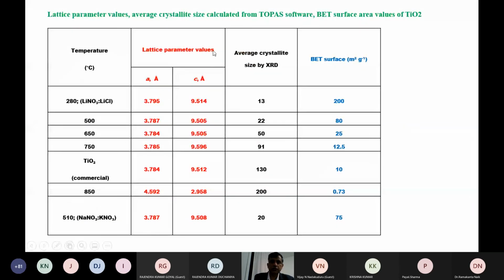Here, we try to prepare the sample by using titanium sulfate. So here we can see nano size material, prepared at nearly 280 degrees, with nearly 200 meters square per gram high surface area. Remember, these contain no surfactant. Again, it is a simple molten salt approach. Any student can do it. One evening, you can come and put the sample in the furnace and go. Next day morning, you can come and filter the sample, and it will be ready for you.